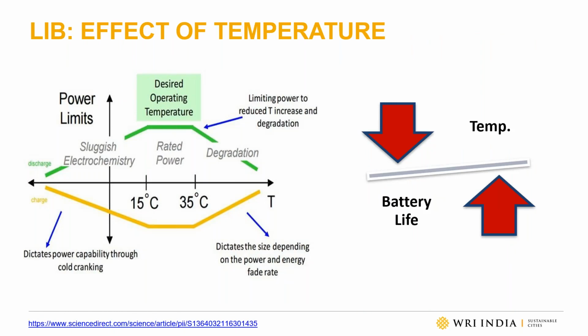So now we'll discuss a few important points related to the use of the lithium-ion battery. First, we'd like to understand how temperature can influence the performance of the battery. Earlier I mentioned how a lithium battery works. During charge and discharge, lithium ions travel between cathode and anode via the electrolyte. With an increase or decrease in temperature, cathode or anode materials may undergo irreversible structural change, which in turn can influence the performance of the battery. To ensure the best performance of the lithium-ion battery, it is important to operate the battery within the optimum temperature range.